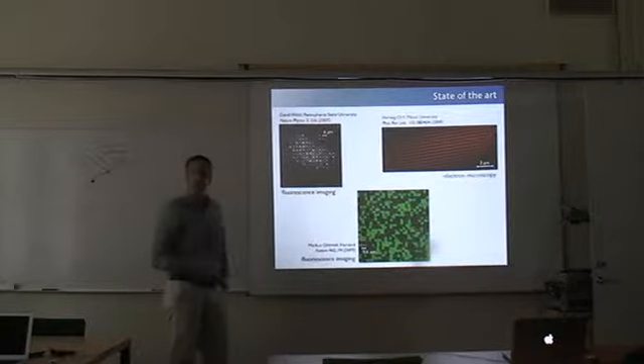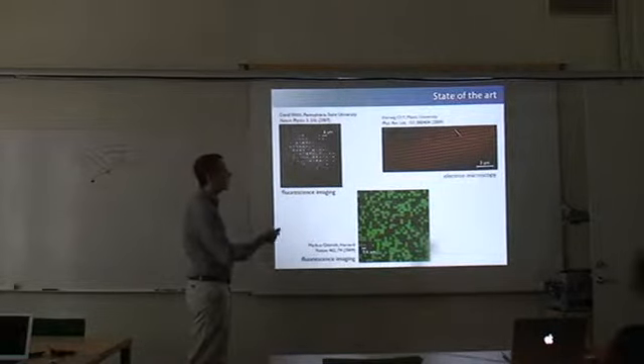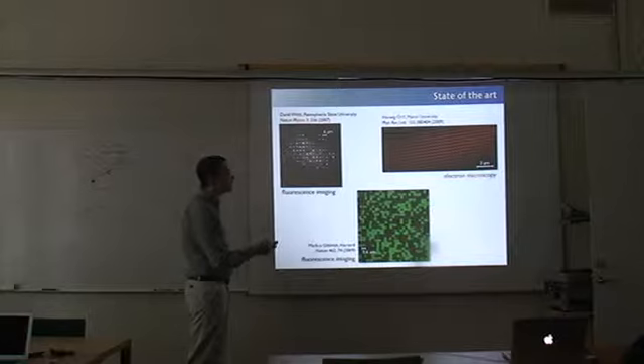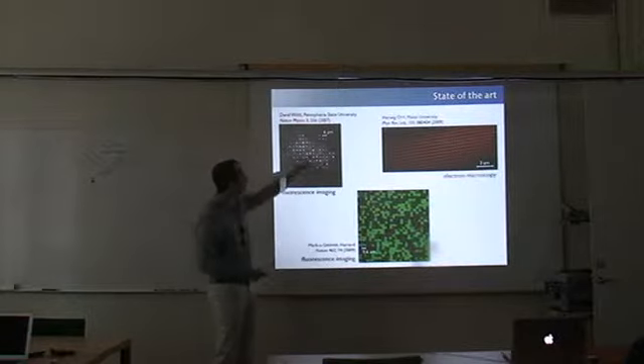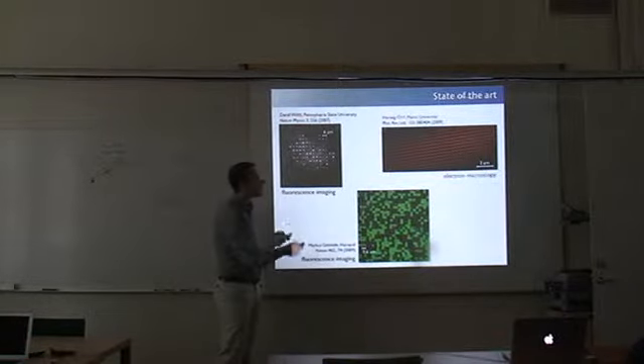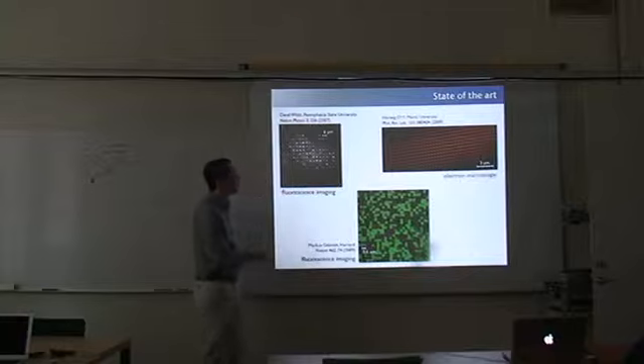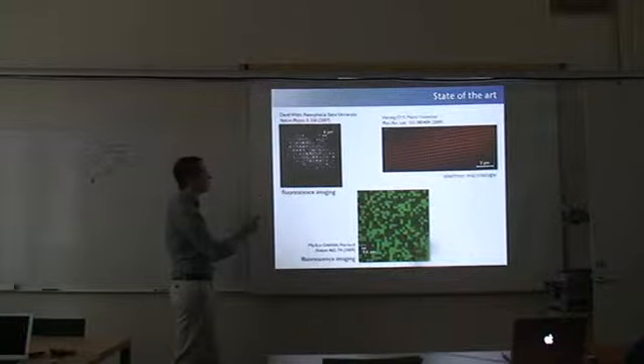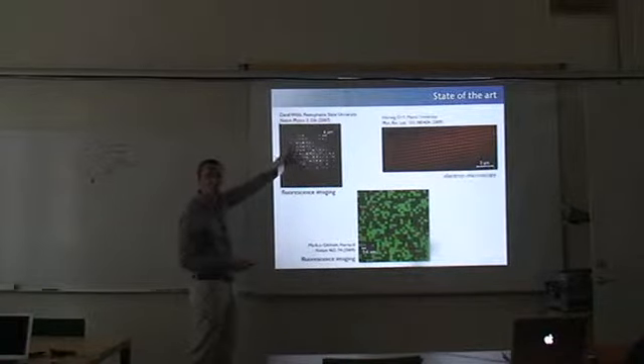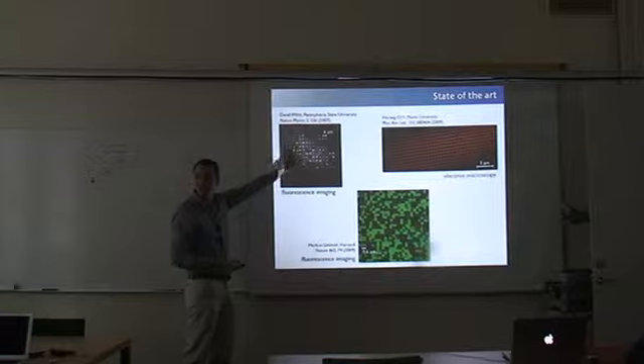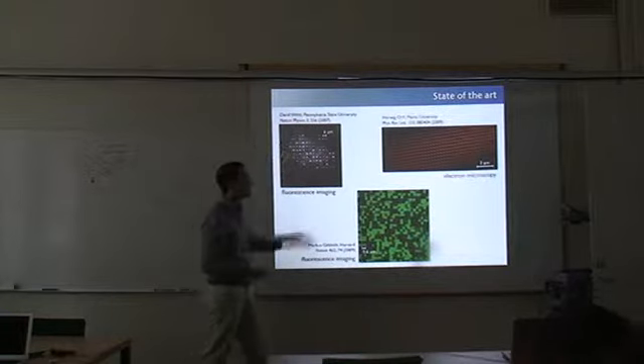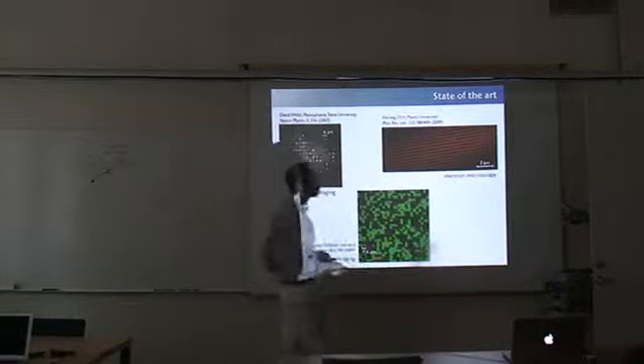For example, for a 2D lattice, a beautifully resolved lattice, lattice spacing 400 nanometers compared to the 5 micrometer here. So this is of course much better for many-body physics applications. This is just too widely spaced for many-body physics. There's just no tunneling between those two wells. Tunnel coupling is basically zero. So it's just independent lattice sites. But this is nice. This is the regime we want to work in.